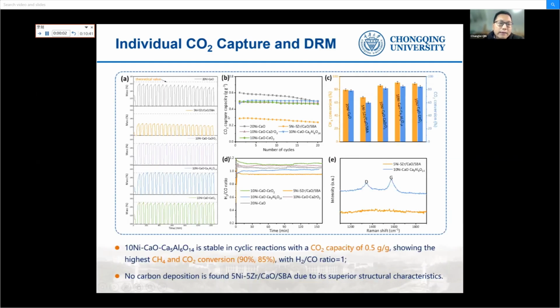Then we tested their performance by individual CO2 capture and individual dry reforming of methane. We saw the DFM supported on alumina is stable in cyclic reactions with a CO2 capacity of 0.5 gram per gram. This capacity is very stable. And in the dry reforming, the highest methane and CO2 conversions are 90% and 85%. The other very interesting one is the DFM supported on SBA, where no carbon deposition was found.